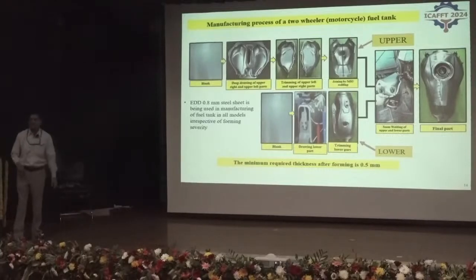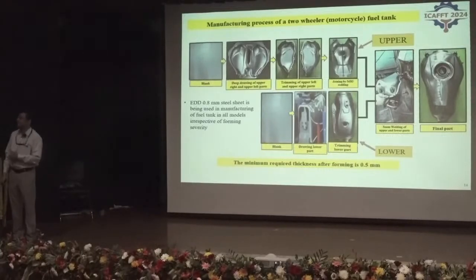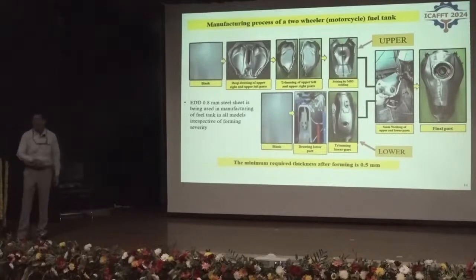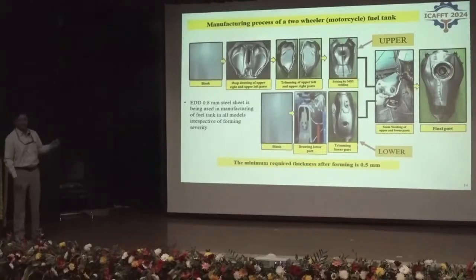And this is presently being manufactured by most of the two-wheelers using one grade called extra deep drawing steel of 0.8 mm thickness, irrespective of the model and irrespective of the forming severity. So we just tried a few different options to bring down the weight of this fuel tank, and yet it should meet the required functional